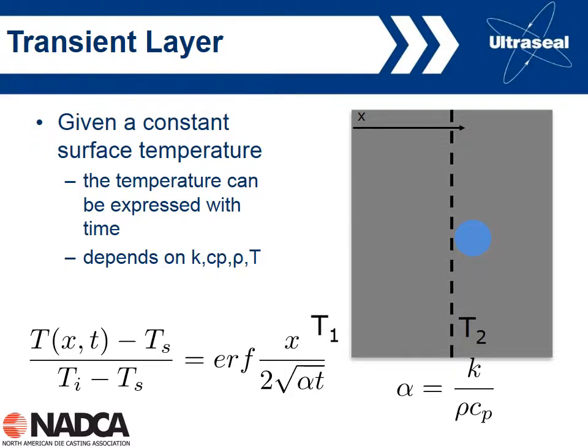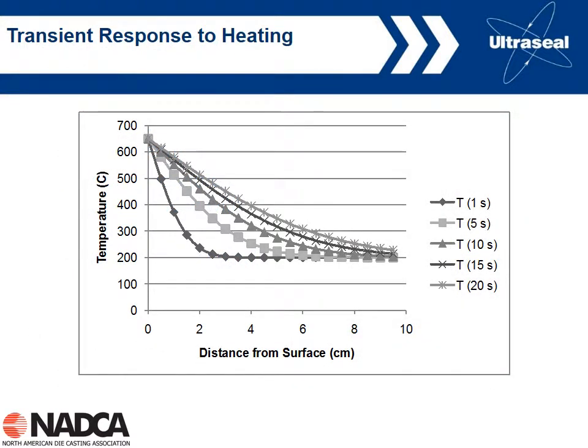We can calculate this transient layer. This is the math shown here. Again, I'm not going to go into detail on the math, but we can use this math to make predictions in terms of both the transient response to heating, which is shown on this graph, and the transient responses to spray, which we'll see on the next graph. This is looking at distance from the surface versus temperature with time. Basically 10 seconds into the cycle or so, the triangle shown here, we've only transferred the heat about 4 centimeters into the die. Again, this is just a little bit more than an inch and a half below the die surface. So obviously we're getting a very slow response in terms of getting heat into the die.